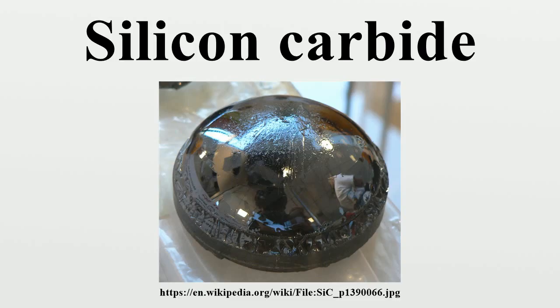Pure silicon carbide can be made by the so-called Lely process, in which SiC powder is sublimated into high-temperature species of silicon, carbon, silicon dicarbide, and disilicon carbide in an argon gas ambient at 2500 degrees Celsius and redeposited into flake-like single crystals, sized up to 2 × 2 cm, at a slightly colder substrate. This process yields high-quality single crystals, mostly of 6H SiC phase.